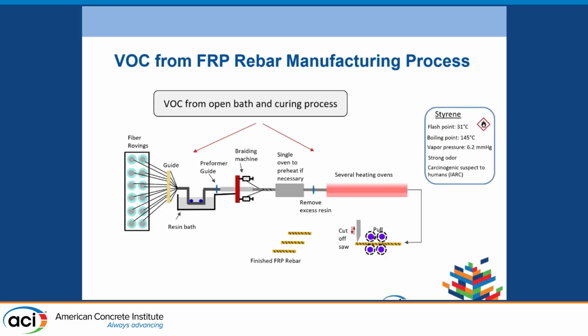Now, the VOCs from the FRP rebar manufacturing process. Here I draw a typical rebar manufacturing process. Basically, the fiber goes through the resin bath. The fiber impregnates the resin, then goes through the preformer guides to remove the excess resin, and then cures either in an oven or in a die. That's the process. It forms the solid rod, the rebar shape, and then it is cut to the design length based on the requirement.